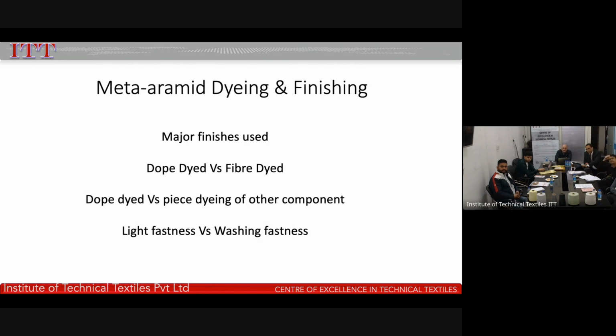Now there is a basic difference between dope dyed and fiber dyed. Dope dyed have the highest fastness, be it light, be it washing fastness. Fiber dyed has its own limitations, since this fiber is very crystalline in nature. It is difficult to dye, and the dyes on the surface fade over a period of time, and thus give a faded look to the fabric.